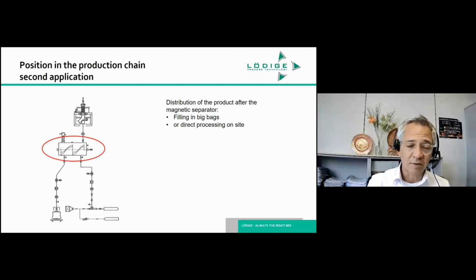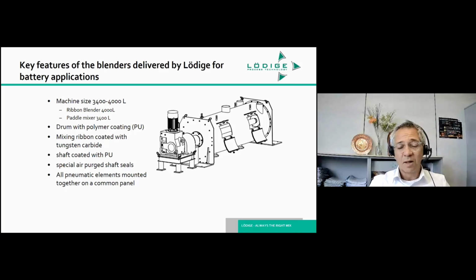The emphasis on the mixing is not that important as in the initial phases, where you have all the individual particles with different physical characteristics. Here, it's more a post-blending. So the mixing is slower, it's much gentler, but nevertheless, in terms of contamination prevention, you still have the high standards. So I'll just give you an insight as to how these machines look. Again, they have key features, one being the size. If you're using mixing equipment up front of 3,000 to 4,000 liters, then the post-mixing uses more or less the same size as well. Mixing action is slow, so here ribbon blenders or paddle mixers have established themselves for this type of duty, giving a much gentler mixing over time.